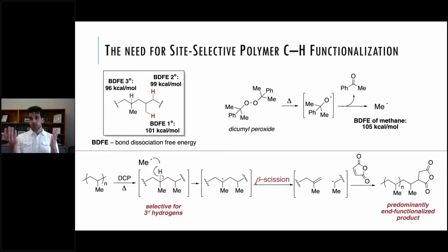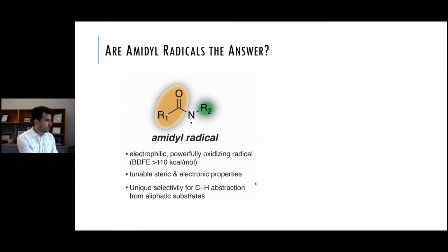This is one of the reasons why only 1% of it is recycled, because if you try to mechanically recycle it too many times, or try to add additives, it will just fall apart and the properties will not be good. So our hypothesis from a fundamental chemistry standpoint is to use a radical to react with polypropylene that has a much higher bond strength than the radicals people previously used. We could use what is called an amidyl radical.